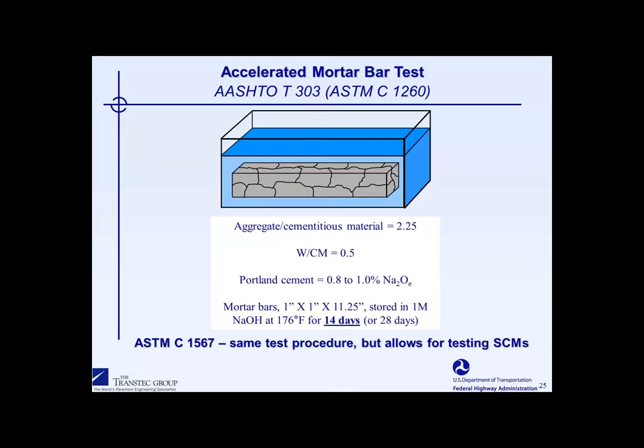One last point I wanted to make is that this test method, which is AASHTO T303, has a parallel test that was passed through ASTM a few years ago. That's shown at the bottom of the slide, ASTM C1567. It's essentially identical test conditions. The only difference is that the test allows one to evaluate the use of supplementary cementing materials to determine how much of that given SCM is needed to control expansion.